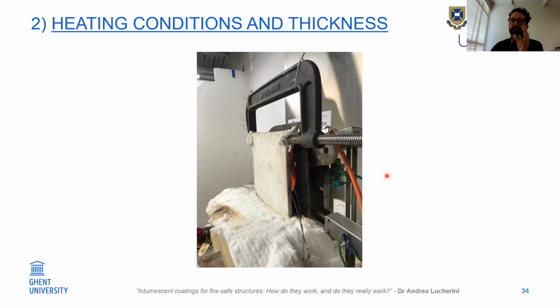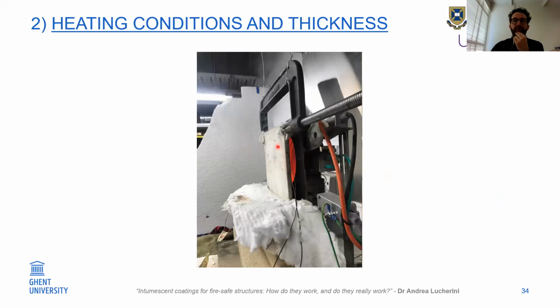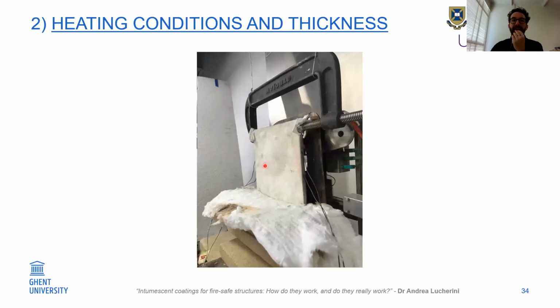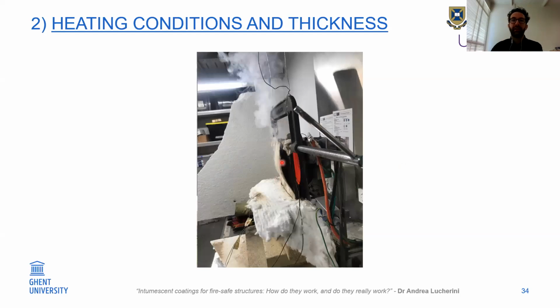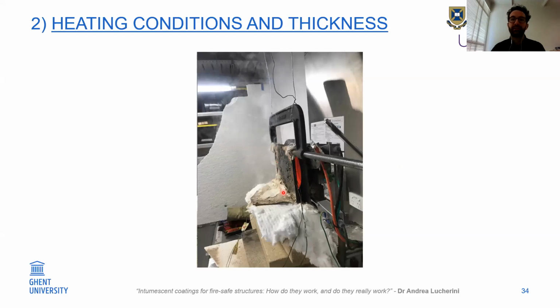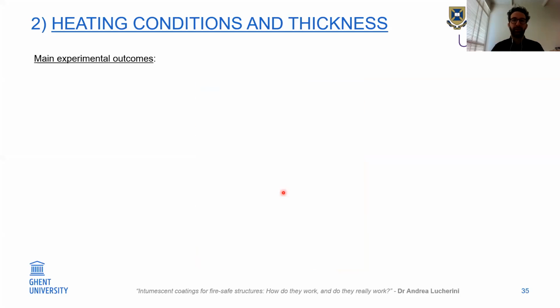What you can see at the beginning, the steel plate starts heating up. Then you can see here the creation of some bubbles because now the coating starts swelling. The coating close to the plate starts releasing gases, but the coating next to those gases is not melted yet, so you cannot trap the gases for the swelling reaction. So the bubbles at the beginning are small, then they get bigger and bigger, until at a certain point they create a sort of cavity, and the coating delaminates until it is completely detached from the plate. And this makes you understand the importance of the fire exposure, and particularly the thermal gradient within the coating when the coating is swelling.